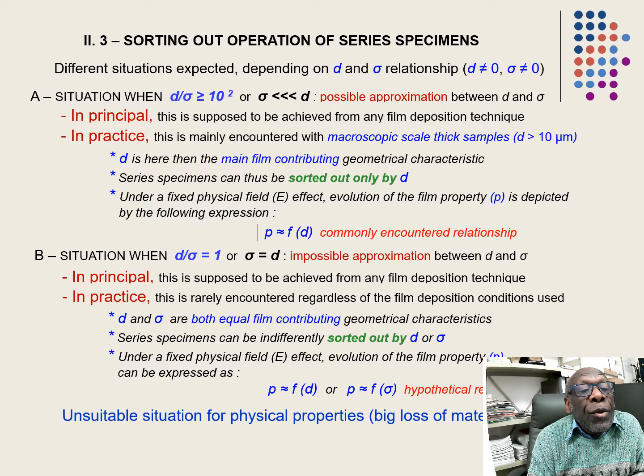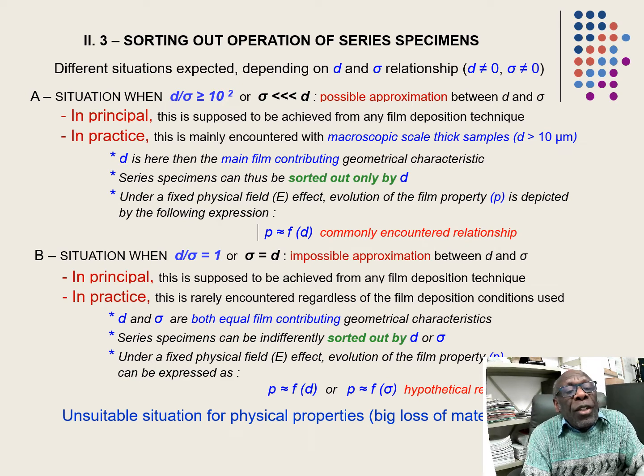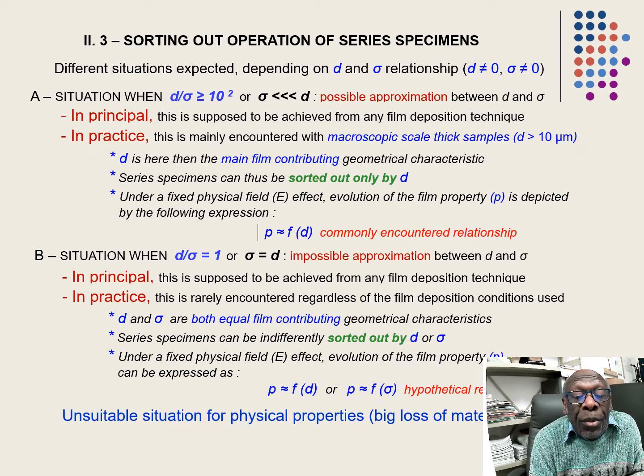In that case, you can see that D is the main contributing geometrical characteristic of the films, and then you can use D to sort your samples. And after sorting your samples, you can study the evolution of the property by the expression P versus D, which is commonly encountered in the literature, but sometimes people use it without any precaution. The second situation is, I can say, for intellectual satisfaction. And this is not really suitable for the measurement of physical property, because we have sigma and D at the same value. Experimentally, it's very difficult to reach that objective. So I will forget it and go directly to the third situation.